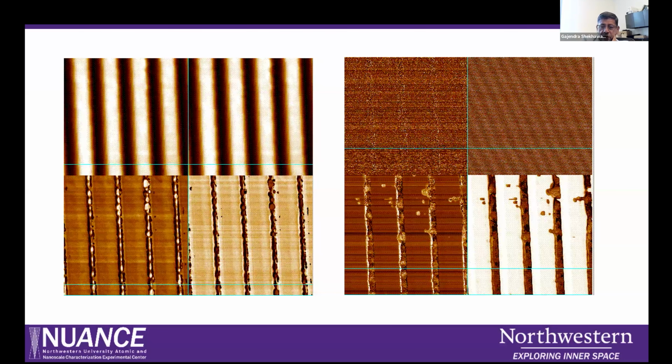And in real time, you can see that some of the features which are not visible in topography, you can see those defects, cracks, delamination across the edges of these trenches. You can see them pretty clearly. So that demonstrates how useful this technique is, especially in the semiconductor industry, where you do the cross sections, cross section SEMs or TEMs. Rather than that, you can use these techniques to find those things.